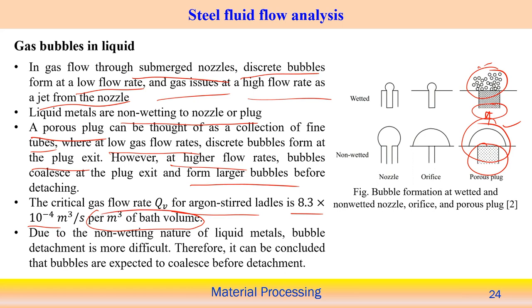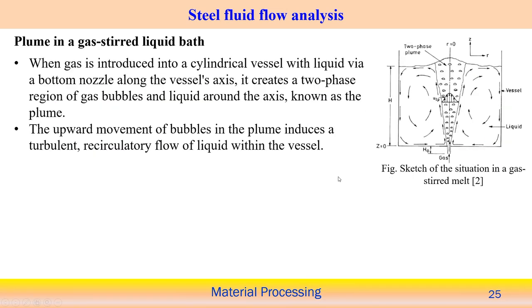Due to the non-wetting nature of liquid metals on the porous plug material, bubble detachment is more difficult. Therefore, bubbles are expected to coalesce before detachment. If the non-wettability is very high for the plug material used, bubbles will coalesce before detaching from the medium.